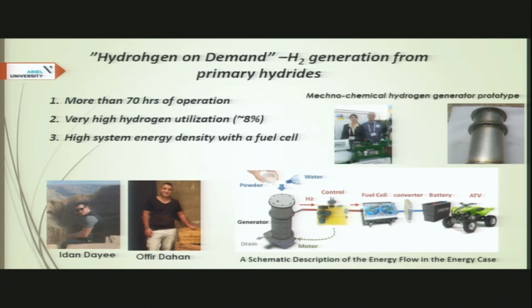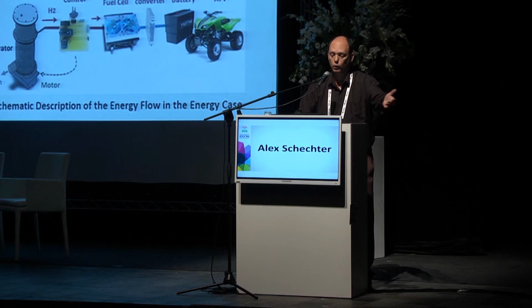Hydrogen generation. Along with my colleague, Professor Idit Avrami, and the student Idan Dai and Ofir Dahan, undergraduate, we have developed a mechanochemical reactor that can generate hydrogen on demand just by pouring in water and hydride salt. For those of you who are interested, we have an exhibition outside. You can go and see and be impressed. We have very high hydrogen utilization. Actually, it's among the highest that has been presented for sodium borohydride. It's a model compound that we use. And we were able to operate it for 70 hours.